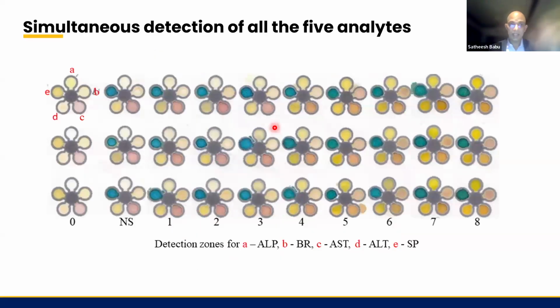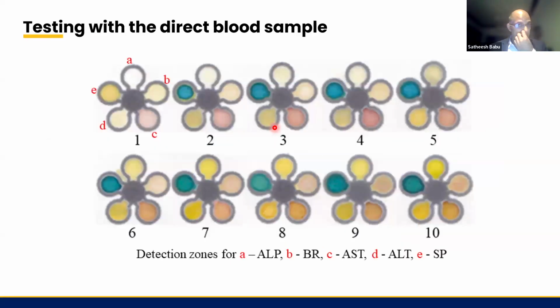And also we tried testing by varying all the 5 analytes at a time. We changed the concentration of all the 5 simultaneously, and also we tested. And this paper device was able to show a quantitative color change. And we tested with the direct blood sample, as I explained. We kept a plasma separation membrane behind, and then we tested with the direct blood sample. We used a finger prick approach, and then we directly placed the blood sample.